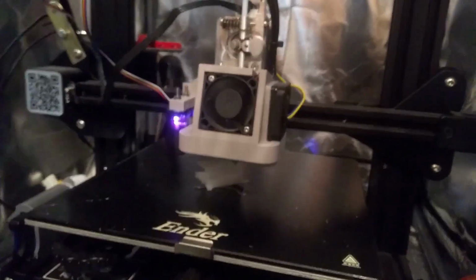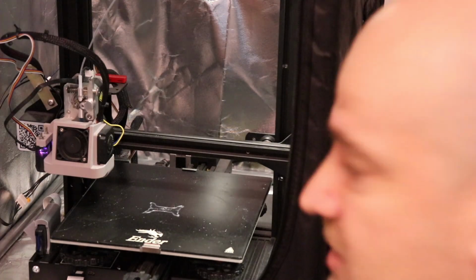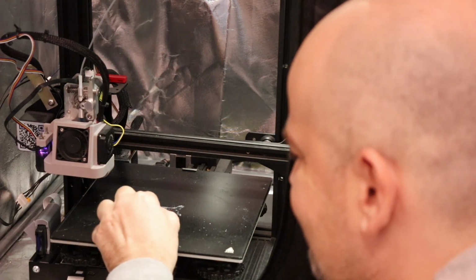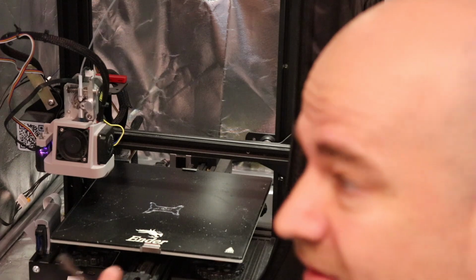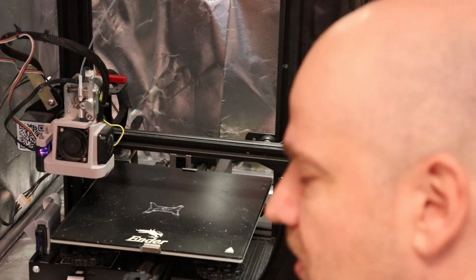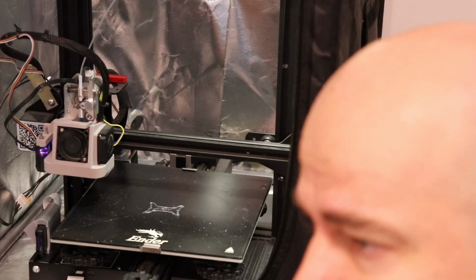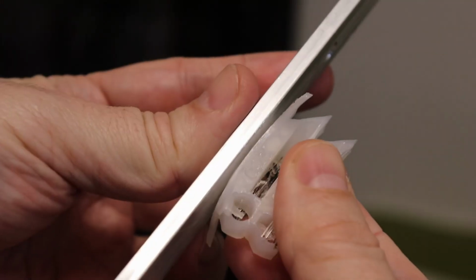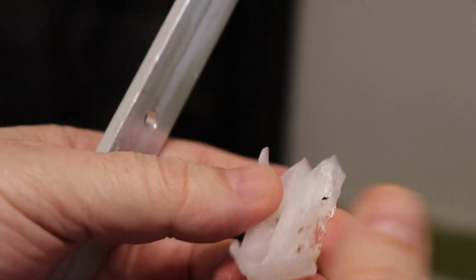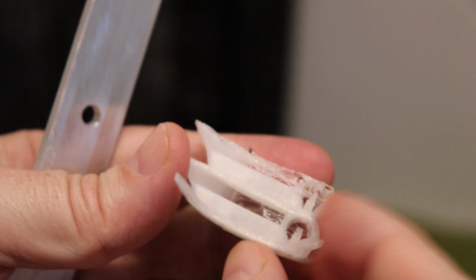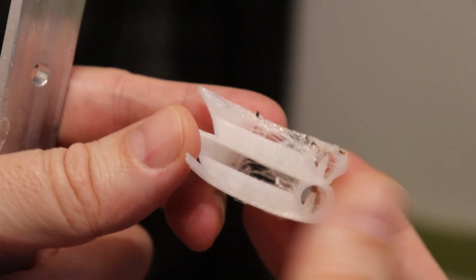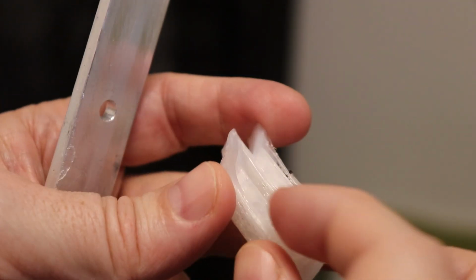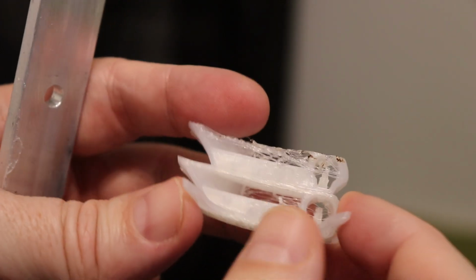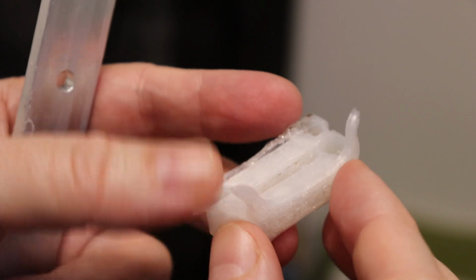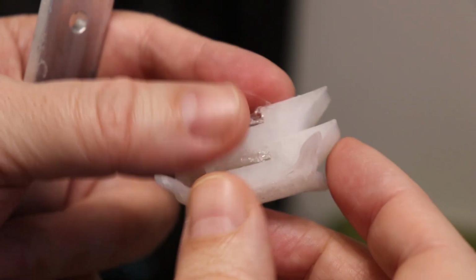And after the second element, it removed from the bed. Now actually the brim sticks well to the bed, so the bed adhesion is good, only this warping is so big that even with good bed adhesion, it curls up and removes from the bed. But two elements are printed, and yes, I have some stringing, but the overhang came out perfectly, and also the bridging, even at 260 degrees Celsius. The problem is this warping, so probably I have to raise the temperature inside the enclosure.